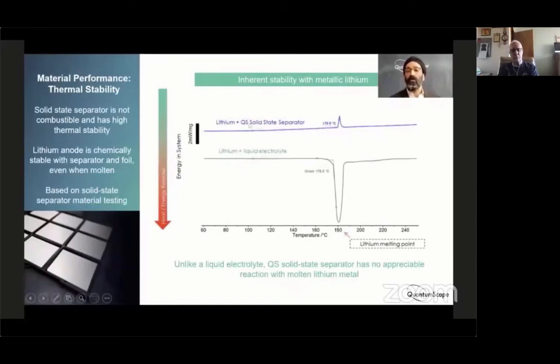And in the case of solid state separator with lithium, even at lithium melting temperature, you see no exotherm. In fact, you see a small endotherm, which represents lithium essentially absorbing energy in order to melt, and no reaction. So this demonstrates the material is in fact inherently stable even to molten lithium, which is a very encouraging result.